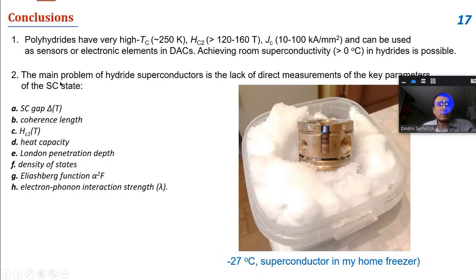There are also several problems of hydride superconductivity, problems of this field. Unfortunately, because samples are not very available for modern instruments, it's quite complex to investigate the key parameters of the superconducting state. It will be important for our future work to measure the superconducting gap, the energy of pairing of Cooper pairs, and heat capacity, London penetration depth, density of states, Eliashberg function, and electron-phonon interaction strength. So this is our plan for the future.